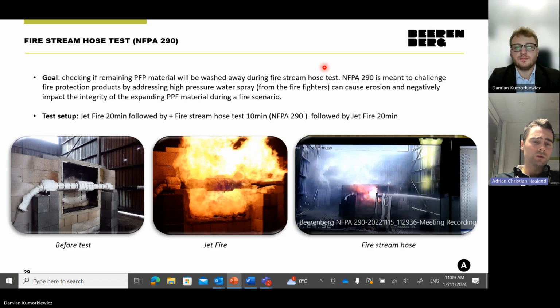How the standard works: you do 20 minutes of jet fire, then you subject it to 10 minutes of water pressure, and then you follow on by doing a subsequent 20 minutes of jet fire testing to see that it can meet 50 minutes in total and provide the same duration to 400 degrees critical that it does originally.